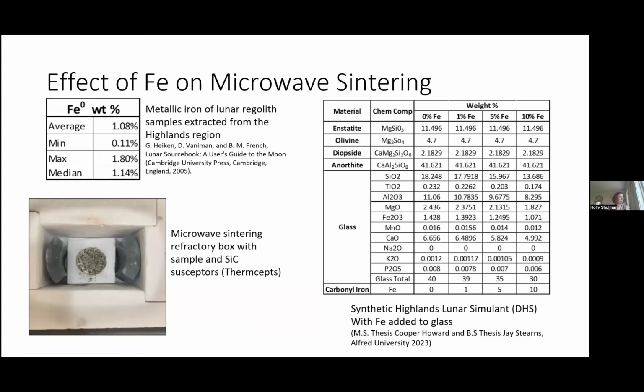So, I've said before how important a good fidelity simulant is, especially in microwaves. We care a lot about things that will cause higher susceptibility, and iron is definitely one of them. So the iron in the Highlands region, some measurements shown in the lunar sourcebook, an average of around 1, as low as 0.1, as high as 1.8, but that range could be even higher than that.